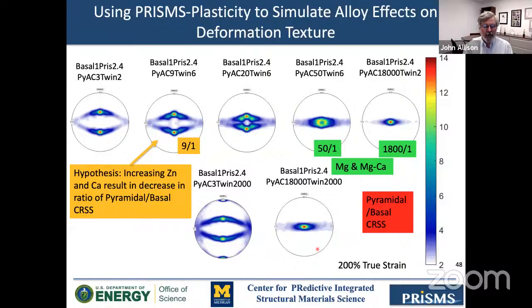We've recently, this is the work of Mohammad Reza Yaghoobi, who's our PRISMS-Plasticity staff person. He can, arbitrarily in the simulation, change the critical resolved shear stress ratio between the slip systems. So here he's simulating magnesium and Mg-Ca, and you see the traditional intense texture develop. And over here, what we think is going to be the right ratio for the zinc calcium alloys, and we see this splitting along the rolling direction for the as-deformed structures. So this pyramidal to basal slip ratio is very, very important.